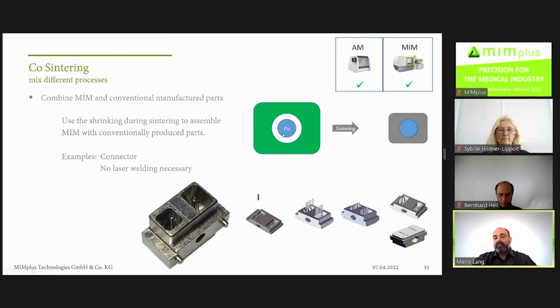What you see here in this sketch is the green part. This is the injected part. You remember we have approximately 20% shrinkage from the green part to the sintered part. So we inject the parts, then we assemble the stainless steel pins, and during the sintering process, the MIM part shrinks onto the pin. And again, it's one solid piece then. So again, what we save is the working step of laser welding.